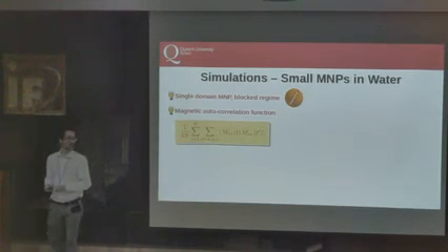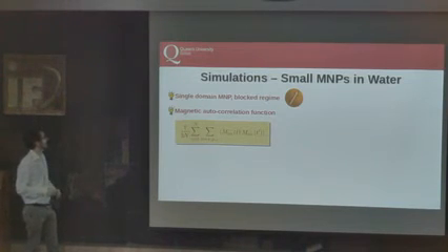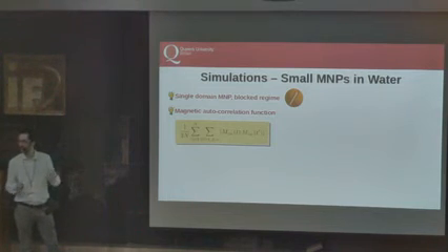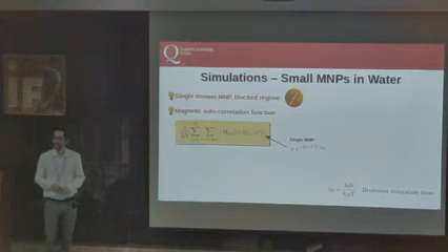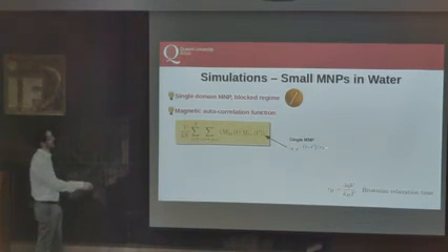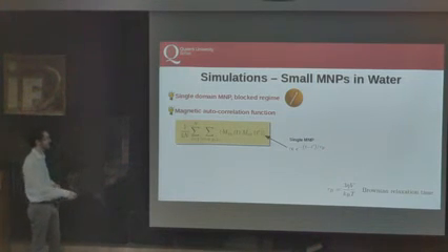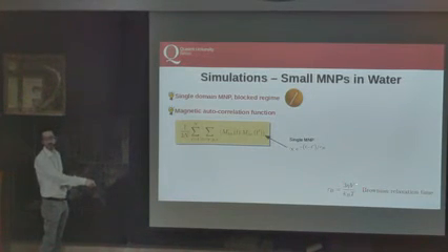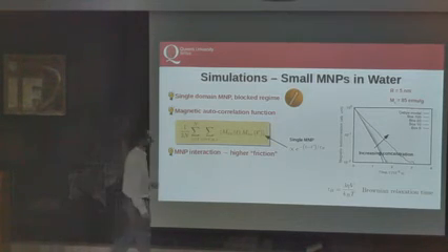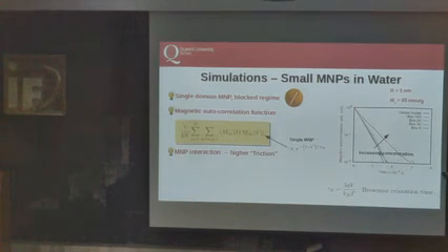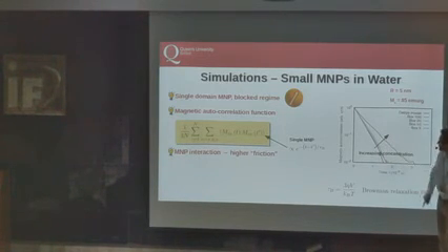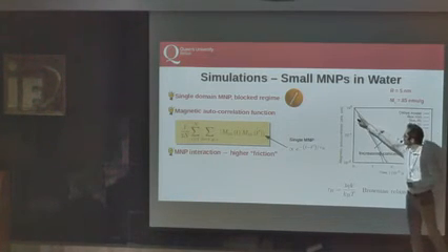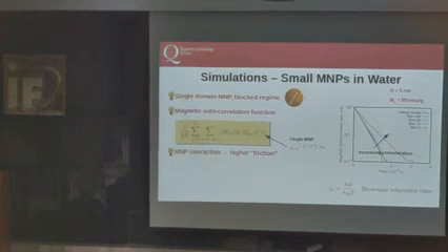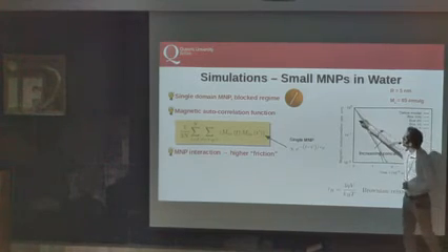We don't have exact results, but we can compute the so-called magnetization, magnetic autocorrelation function from the simulations, from the spin dynamics simulations. We also expect this to decay exponentially. We can relate the exponential decay to the Brownian relaxation time, which in the case of a single particle, I want to remind the expression. Those are the results for small, this time magnetic nanoparticles in solution. We use simulation boxes of different size. This is not important, just to say that by increasing the concentration, there is a clear deviation from the expected Debye single particle model to the results at very high concentration.